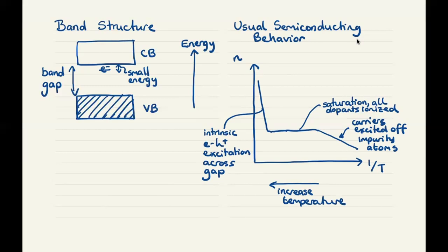And at higher doping concentration, if we had more dopants, then this whole curve would shift up. So higher dopant concentration, there'd be more carriers excited off the impurity atoms before we reached the saturation region. And then eventually, again, at very high temperature, intrinsic electron hole excitation across the gap occurs again. So this is at higher doping concentration.